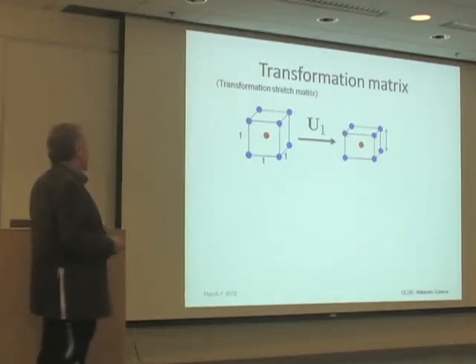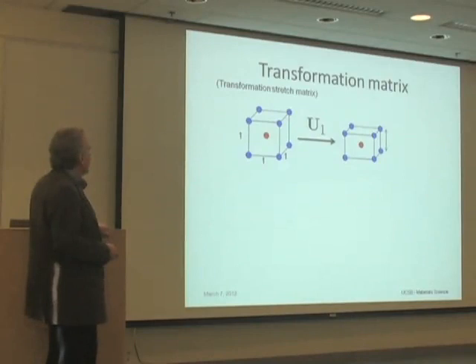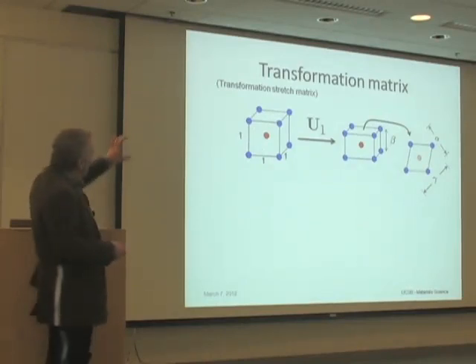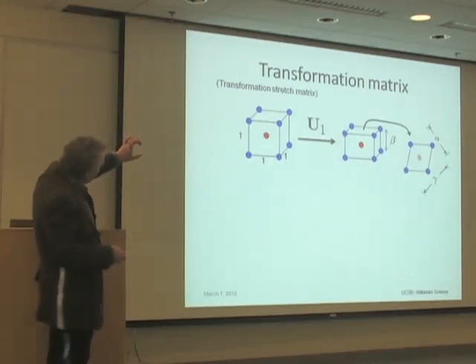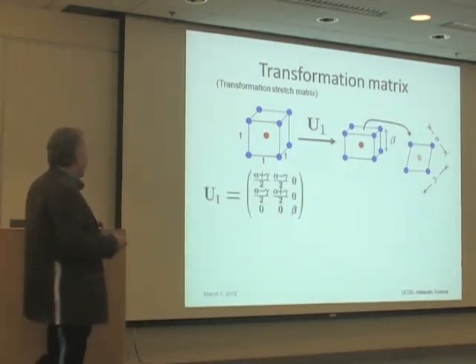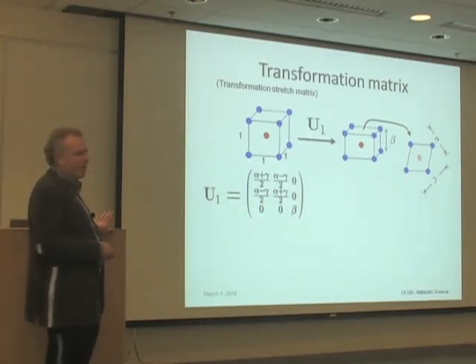So here's a different martensitic phase transformation that's a cubic to orthorhombic case. So that would be, here's some B2 structure in it. And it shortens at the phase transformation, and that shortening is described by this constant beta, lattice parameter beta, and the top of this becomes, instead of a square, a rhombus, and there's two other lattice parameters, alpha and gamma, here, and the matrix which describes the linear transformation from here to here, you can think of that as a linear transformation, is that matrix. It depends on lattice parameters. That's going to play an important role in my talk.